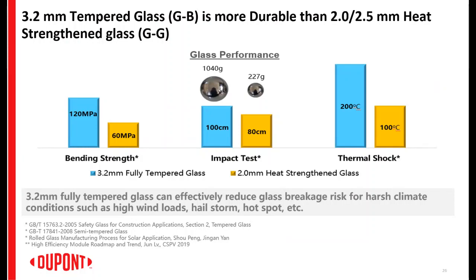I initially spoke about the use of different glasses in module structures. This table shows that the tempered glass used in glass backsheet modules has stronger mechanical properties and thermal shock resistance than the heat-strengthened glass typically used in glass modules. These tests simulate the impact on the operation of PV modules in the field.